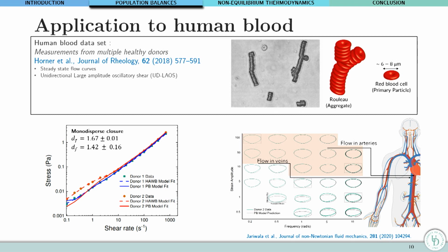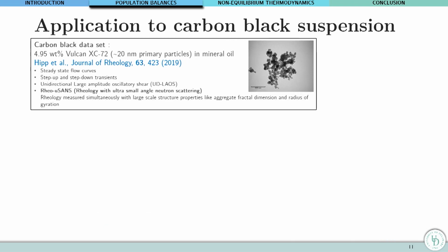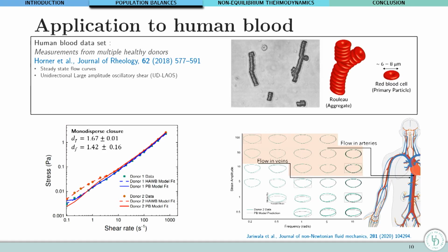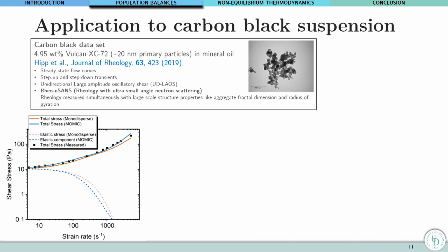We also examined the behavior in transient flows, as for example the one that you obtain using unidirectional large amplitude oscillatory shear, where you superimpose oscillatory shear with steady shear, and you represent the behavior in terms of a curve that shows the stress versus the strain for different values of strain amplitude and frequency, and one can see reasonable agreement at high values, but some disagreement at lower values in this analysis. So the next level: this analysis here was performed, for simplicity, by using a coarse-level description of the microstructure where all the aggregates were assumed to have the same effective size, which was allowed to vary with varying shear rate.